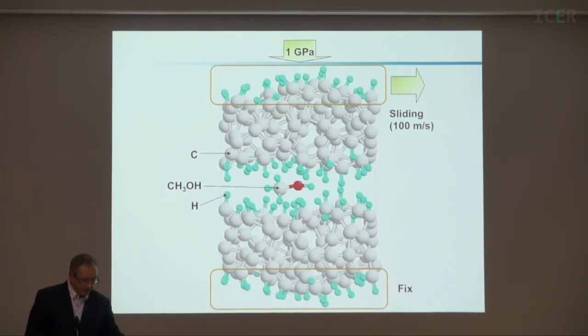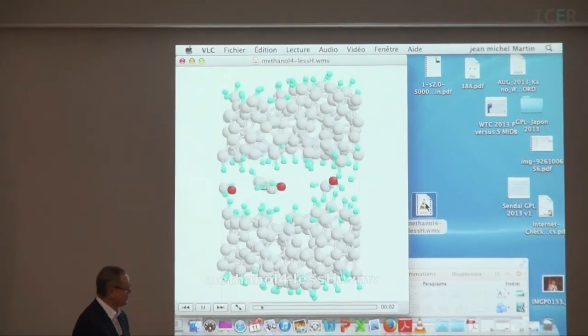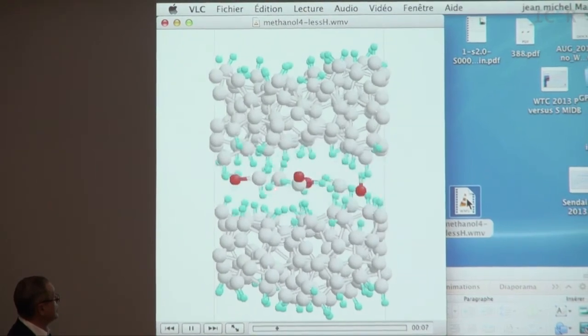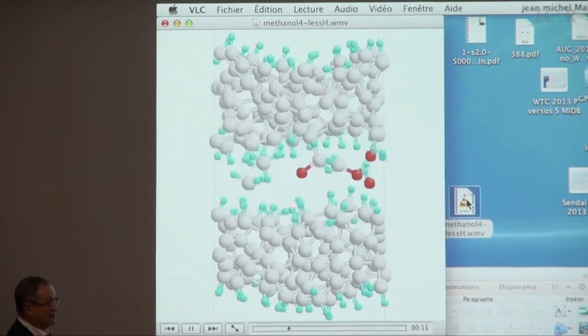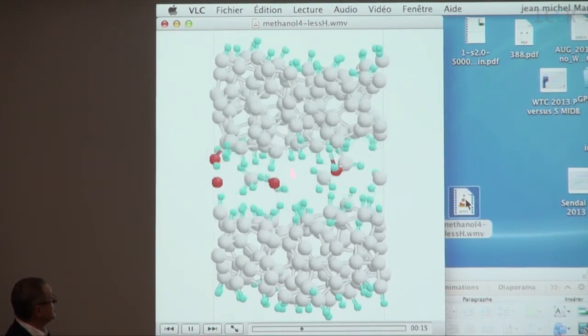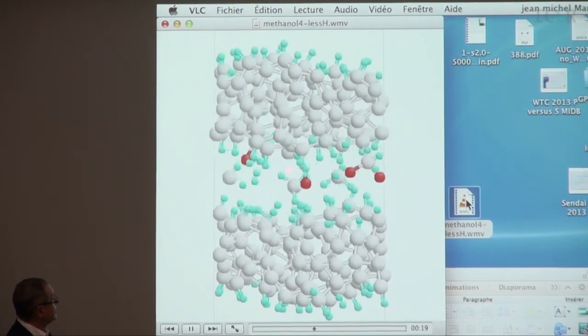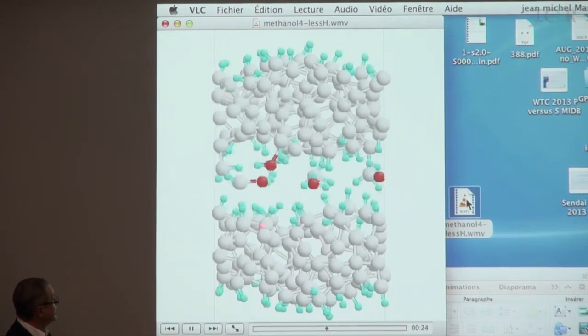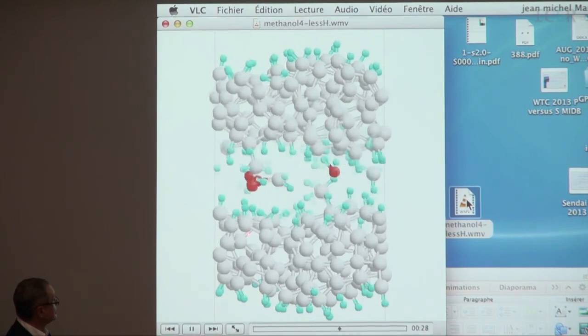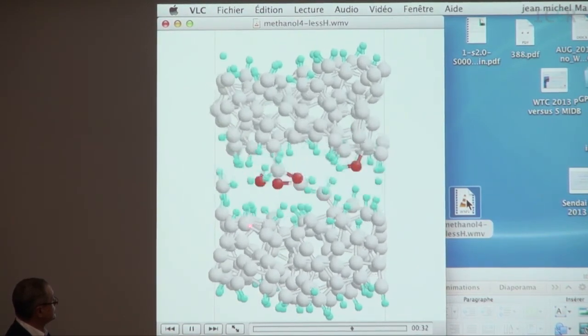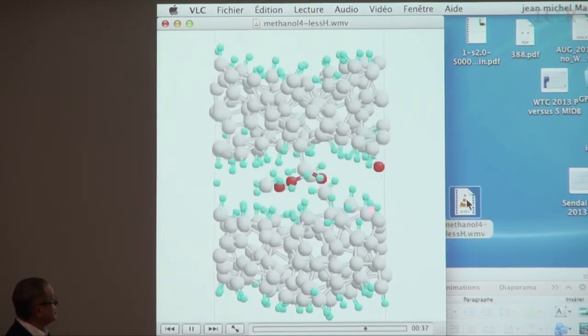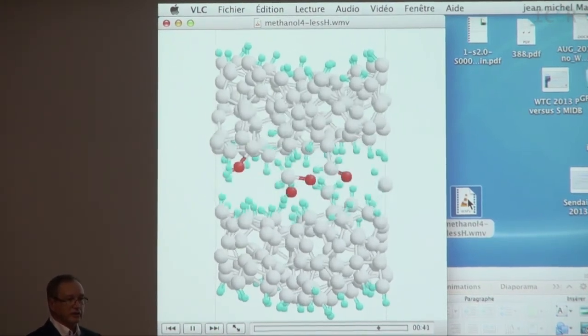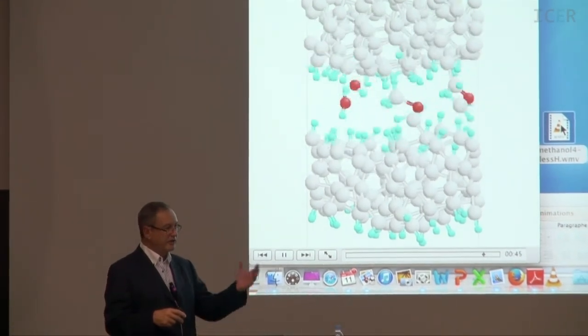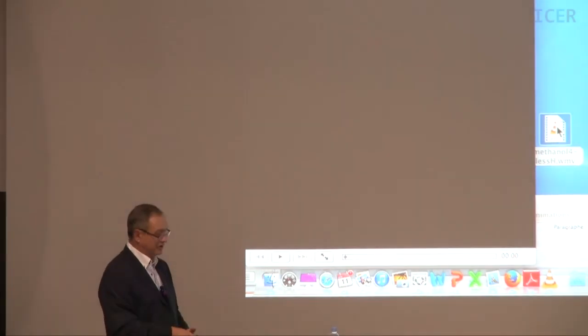Maybe I can show you. This is the experiment, computer experiment. And there are four methanol molecules. But you can see that the methanol molecule is cut in small pieces. And each piece reacts with the carbon coating. Here, methane is formed. And at the end, you will see some OH termination coming on the surface. Here, for example, OH termination. So if you have a lot of molecules, at the end, you get a lot of OH termination. And importantly, the surface becomes hydrophilic because there is a lot of OH on the surface. So this mechanism has been confirmed by a computer simulation.